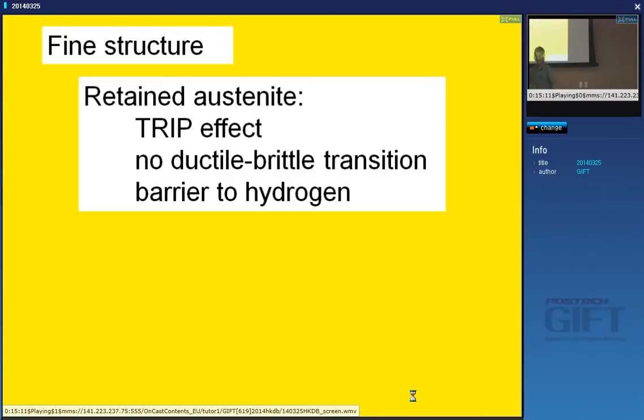Besides the fine structure, can you think of any other advantages to having a structure which is a fine mixture of ferrite and austenite? Think about the austenite — why do we often want austenite inside our material? During deformation it undergoes phase transformation — we call that effect TRIP: transformation-induced plasticity. We have a fine structure and the retained austenite can undergo transformation, which helps us get more ductility — we'll go into that in more detail in a later lecture.